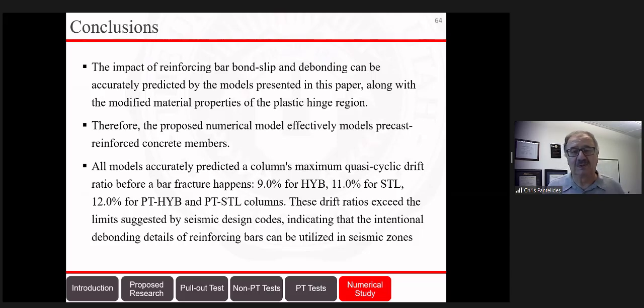The post-tensioning was good. The post-tensioning reduces the residual displacement, and the fiberglass bars reduce it even more. And what's good about this is that since we use fiberglass spirals and some of the longitudinal bars were also fiberglass, that means these columns will have much less corrosion than the columns we build today. So in conclusion, I would say that we really did achieve a more durable bridge, a very well-performing seismic bridge bent, and I look forward to seeing this implemented in the future.